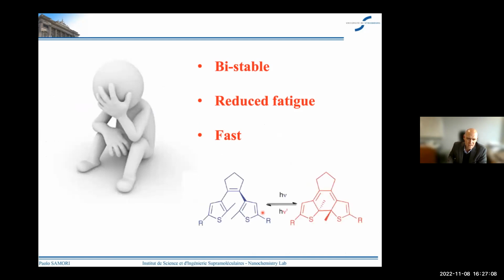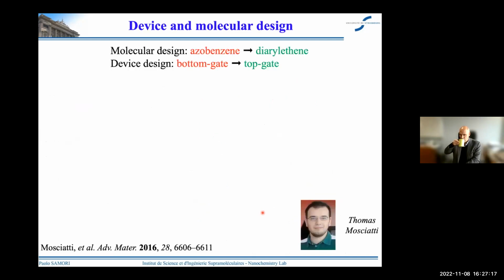Now, what if we want to go further, and we need to try to improve our system in terms of getting a photoswitch that is bistable in the two states, that has reduced fatigue, and that is a much faster switch, because for digital electronics we need fast switches. And so we decided to move to diarylethenes, and that was done in collaboration with Professor Stefan Hecht at Humboldt University, Berlin. This was the thesis of Thomas Mosciatti. And so we changed the molecular design from azobenzene to diarylethene, and the device design from bottom gate to top gate.